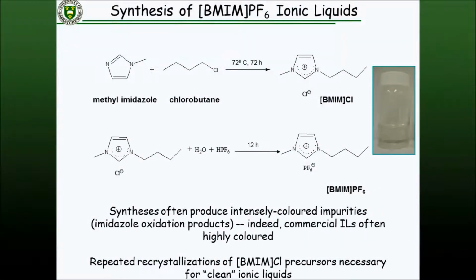Here's a not particularly difficult synthesis, but industrially you don't typically get nice, clean, clear ionic liquids like this. The imidazole in air easily oxidizes. You get very colored impurities that are very hard to work with and very hard to separate from the ionic liquids once they're made. So most of the synthesis is actually done under nitrogen. Distill all of your precursors under nitrogen. Very mild reaction in toluene, methylimidazole chlorobutane, for example. You get your chloride salt, and then do an ion exchange with the chloride salt to get your hexafluorophosphate salt.